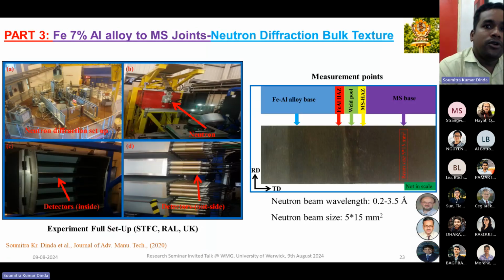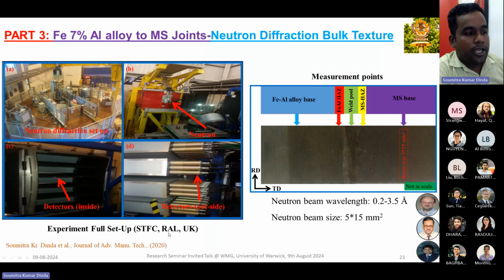So we know the microstructure and microtexture, but suppose our welding material thickness is 4 to 5 millimeter or say 10 millimeter, then this microtexture will not replicate the total mechanical properties which we are getting. So for that we did the neutron diffraction study for the bulk texture. For this study, our material thickness is 5 millimeter. The neutron beam is 5 by 15, and the neutron wavelength we used is 0.2 to 3.5 angstrom. And this experiment we performed at RAL, Rutherford Appleton Laboratory in the UK.